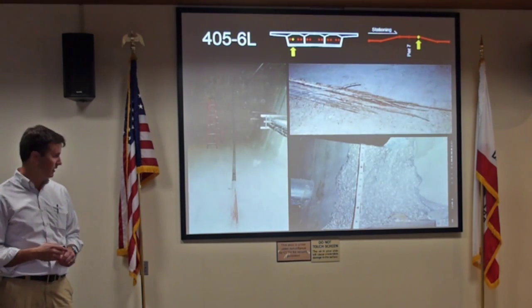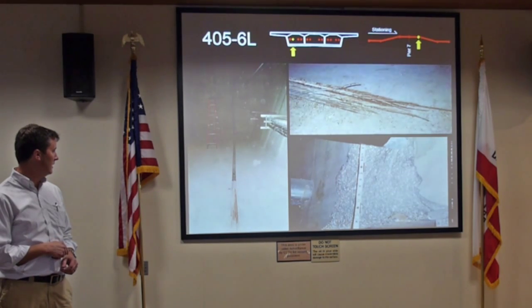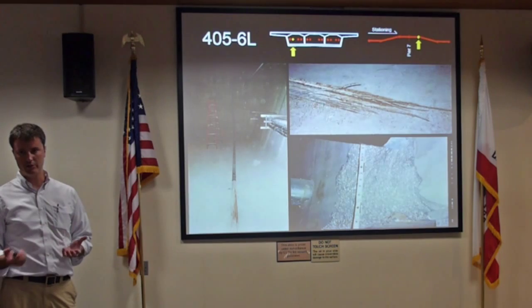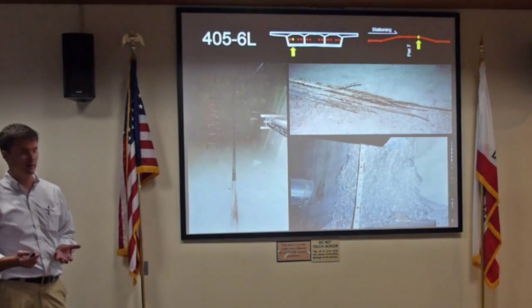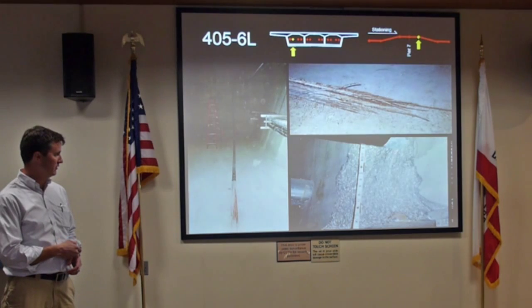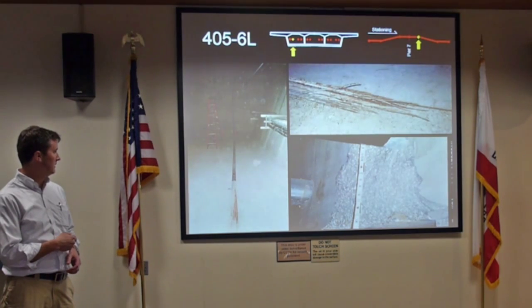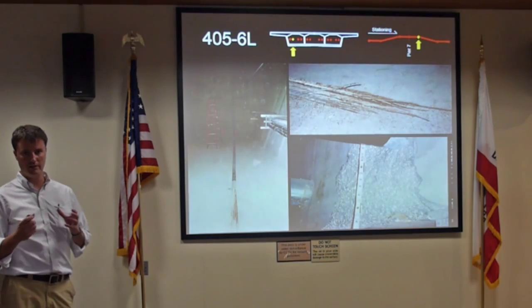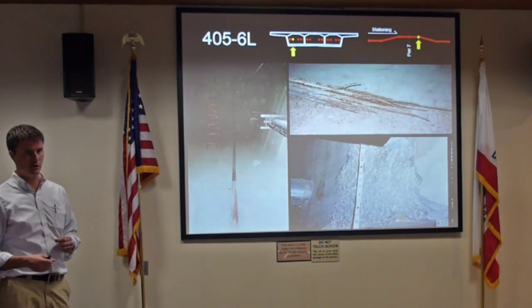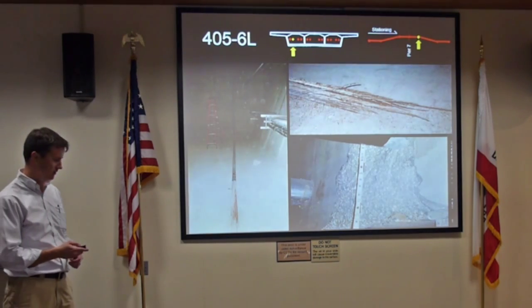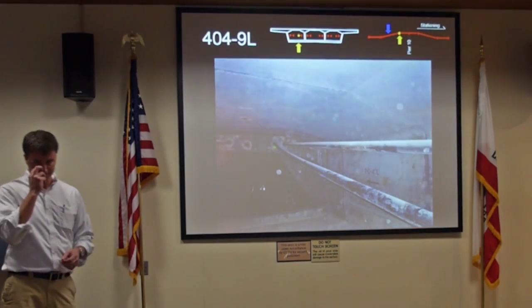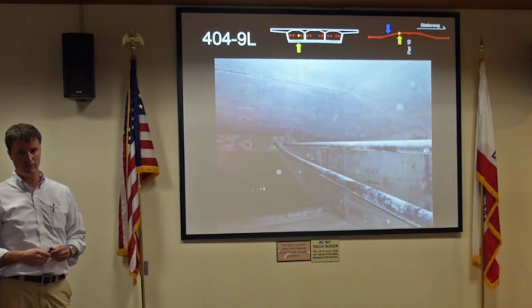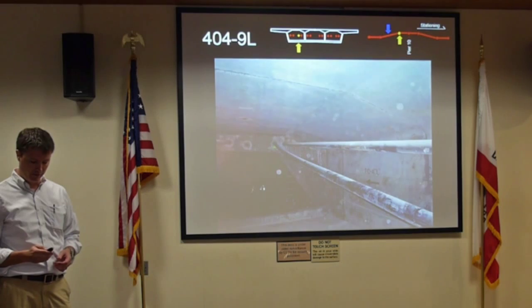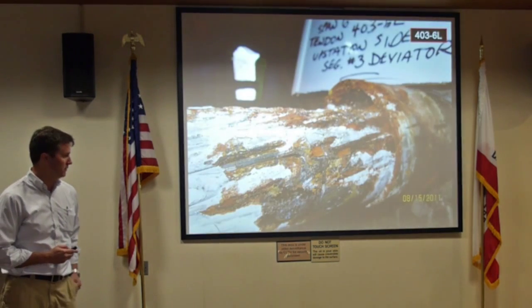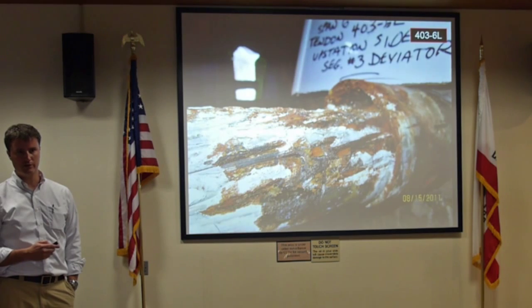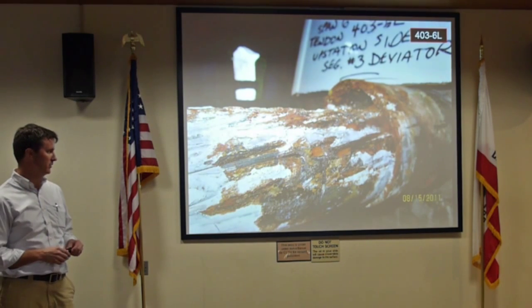These things are actually supporting, or excuse me, in tension, essentially about 1 million pounds. So a significant amount of force, to the point where it blew out some of the concrete, and you can't see them here, but there are whip marks on the inside of the concrete where, when this thing fails, it thrashed around until all the tension was released. Pretty violent. A couple months later, another maintenance walk found another one. So DOT became very concerned at this point, and so we inspected all these external tendons at the high points, which seem to be where this failure is occurring.